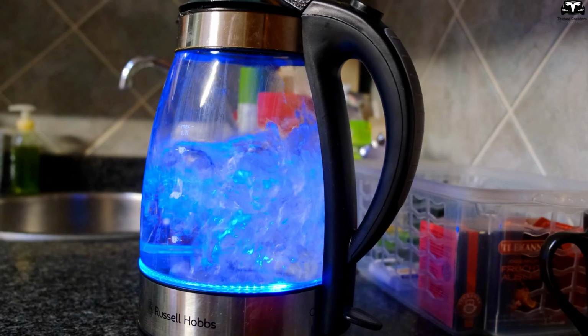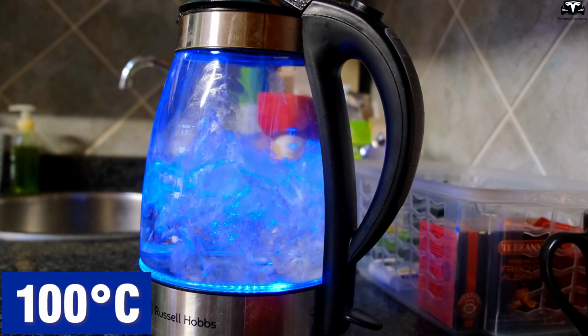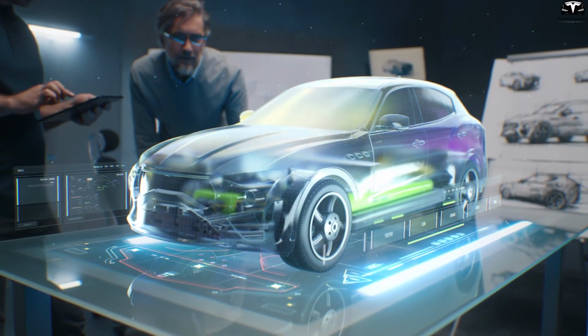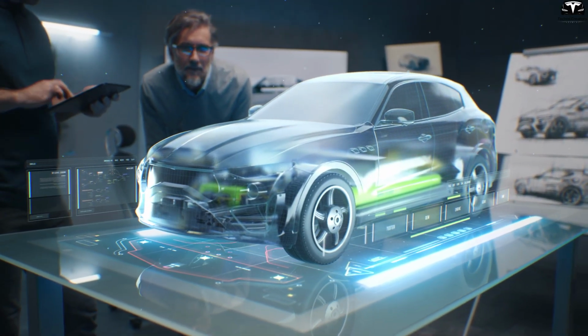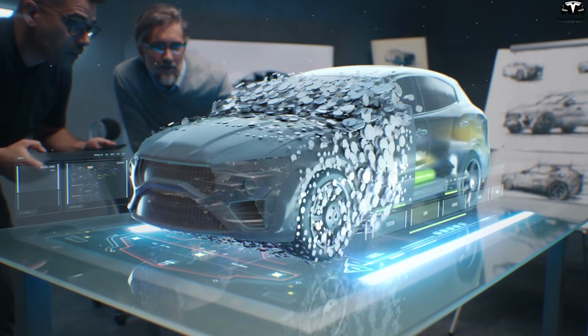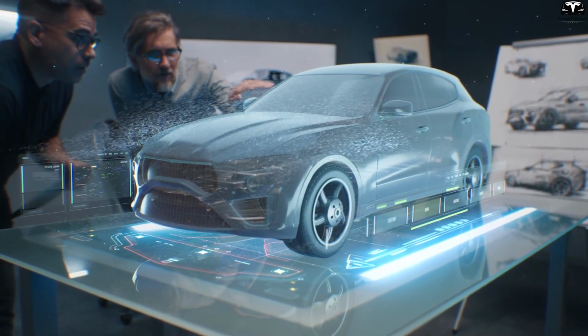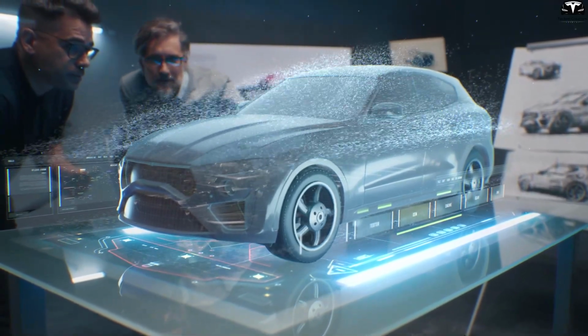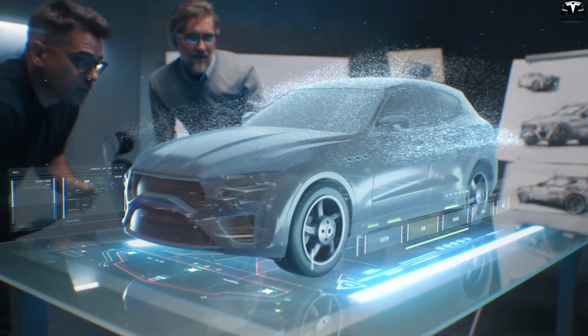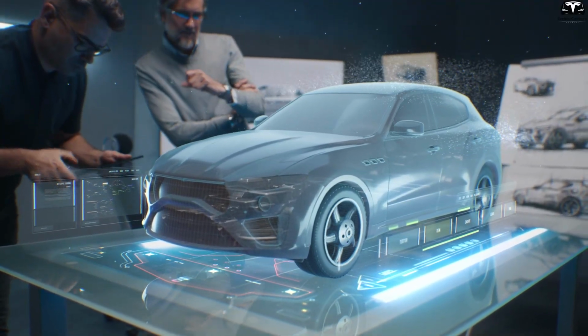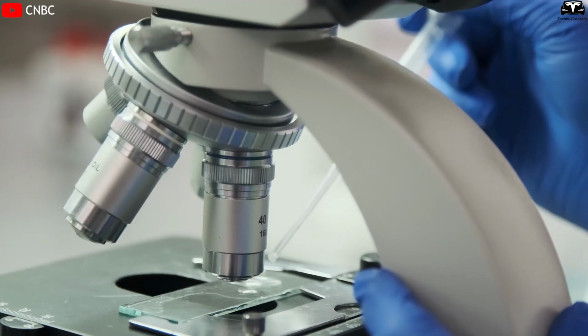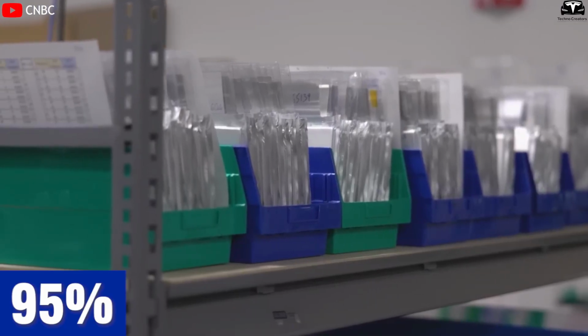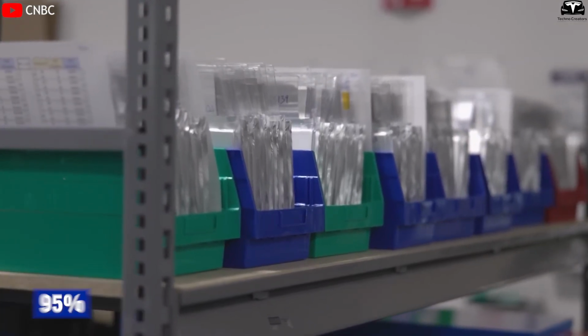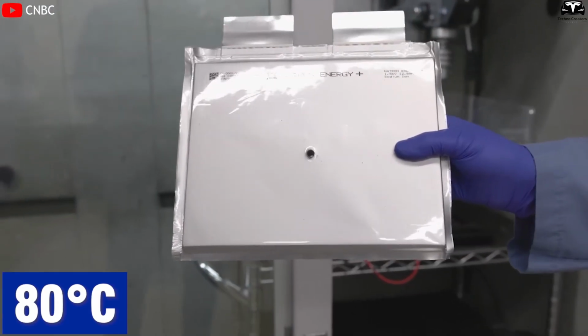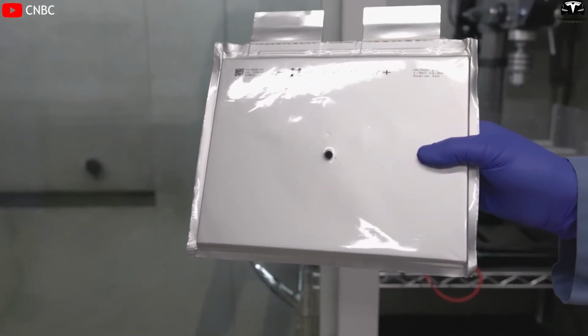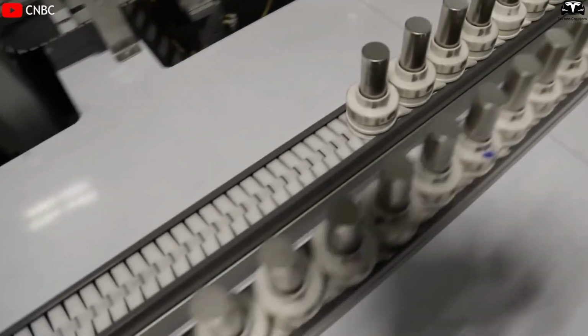However, the boiling point of water in WiPSE is about 100 degrees Celsius, which can lead to evaporation when the battery operates at high temperatures above 60 to 70 degrees Celsius during fast charging or continuous use. These temperatures are common in many electric vehicles today, so developing polymers that better retain water and implementing specialized cooling systems are essential. Laboratory tests have shown that new polymers can retain up to 95% of their water content after 1,000 hours at 80 degrees Celsius, helping to prolong battery life and stabilize performance.